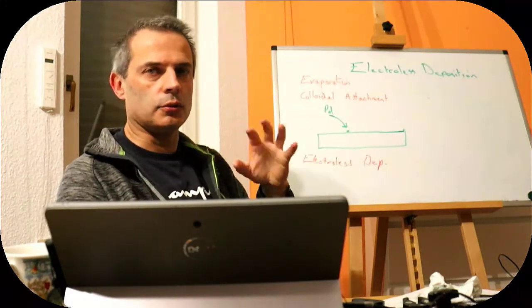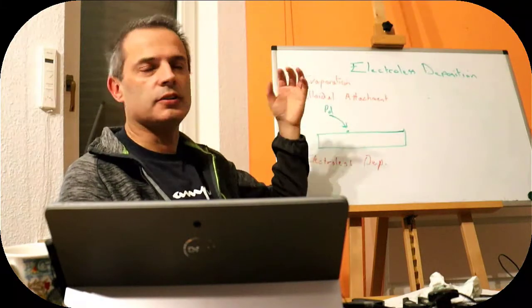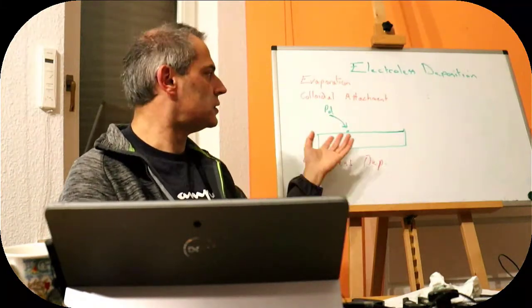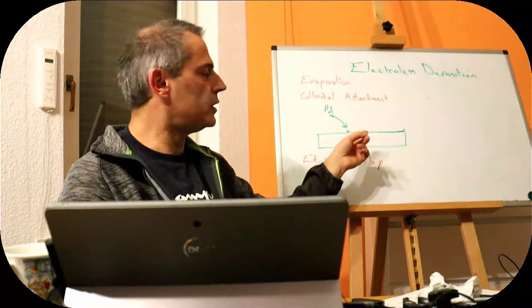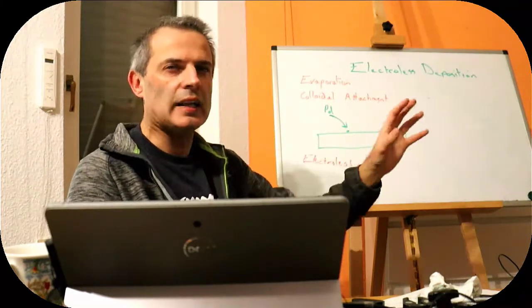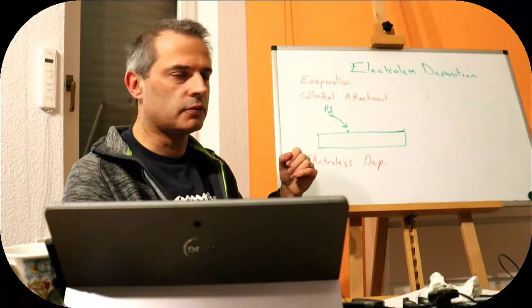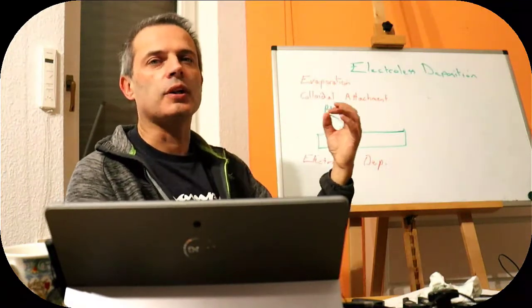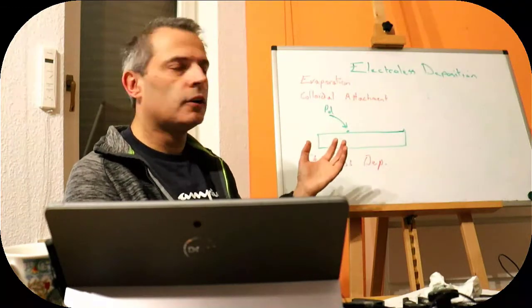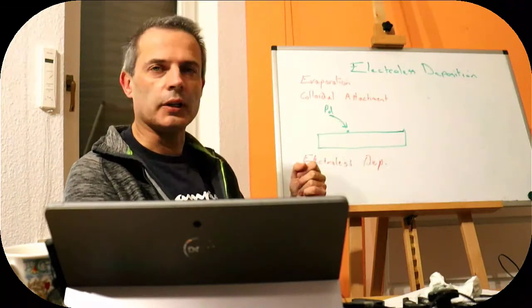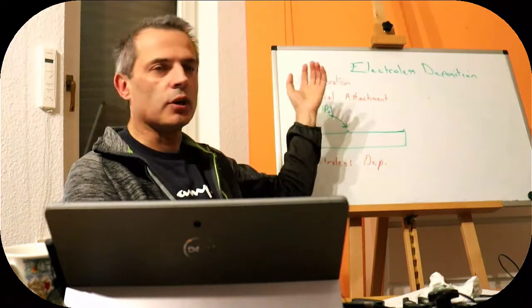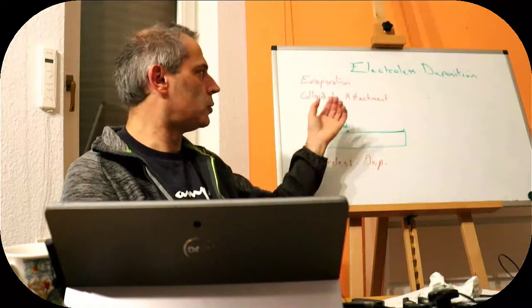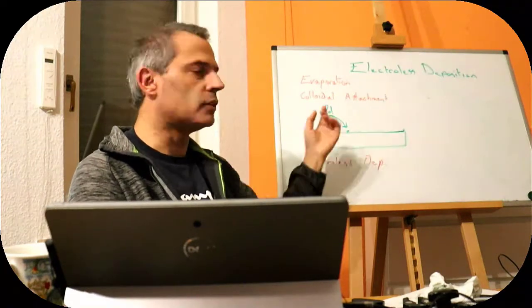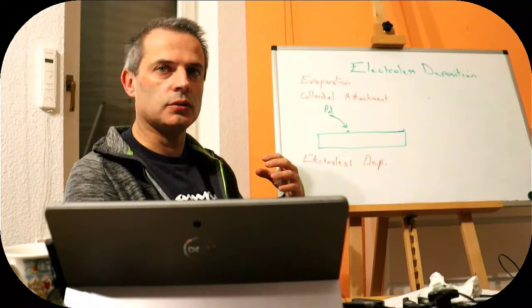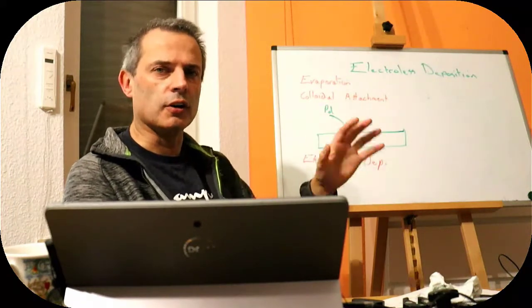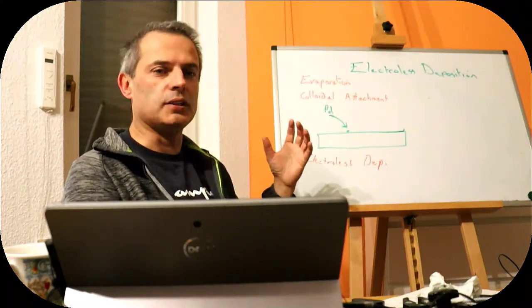Or we could, of course, do the easy way and evaporate some metal onto the surface. We don't need very much, because it doesn't need to conduct from one side to the other anyway. We just need single particles, so we can just give it a little bit to dust the particles on the surface. We could also evaporate something else. If we take an equivalent process for making carbon nanotubes, we can evaporate a metallo-organic compound to make a layer, or we could just paint it on, and then we can reduce it afterwards to the metal, in that case in a hydrogen environment, but that's because we've got money to do so.